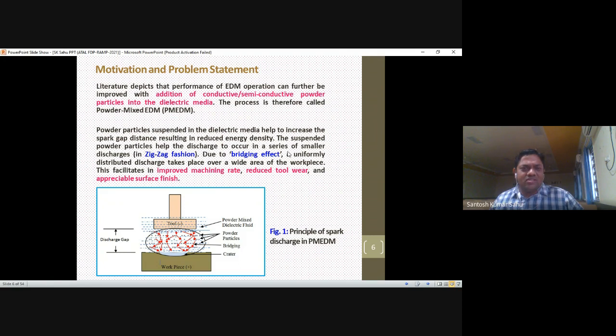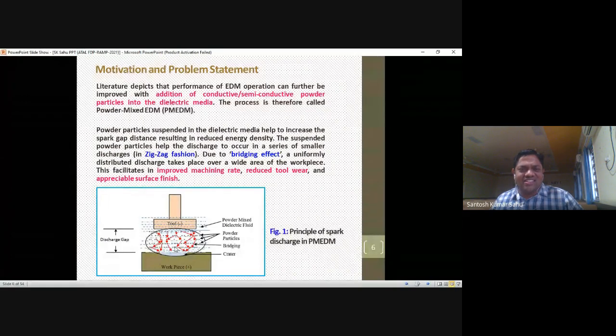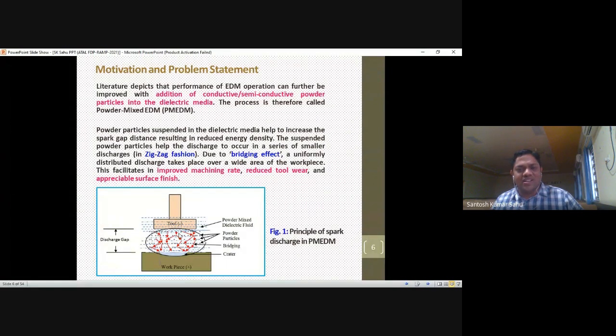So again you have to see the suspended powder particles. What are the suspended powder particles available between the two electrodes? They help the discharge to occur over a series of smaller distances, in a zigzag fashion. Before, when the powder particle is absent, the spark is directly bombarded onto your workpiece. The spark is not uniform, and based on that the metal is also removed. But here we can see a zigzag fashion, because the spark is uniformly distributed with the help of the powder particle, and the powder particle acts like a carrier of the spark from your tool to the workpiece.